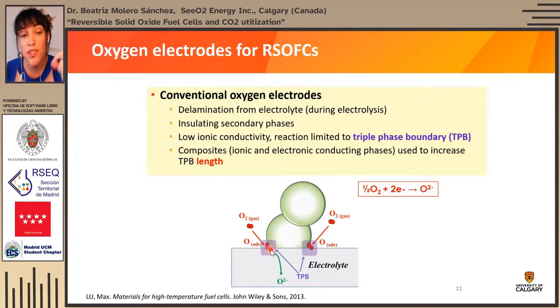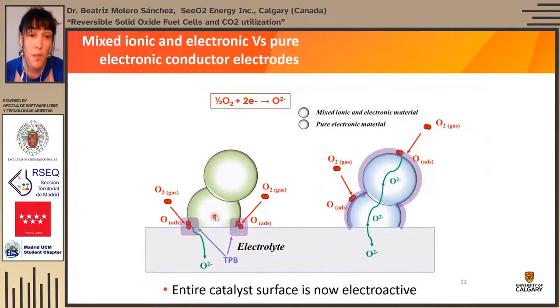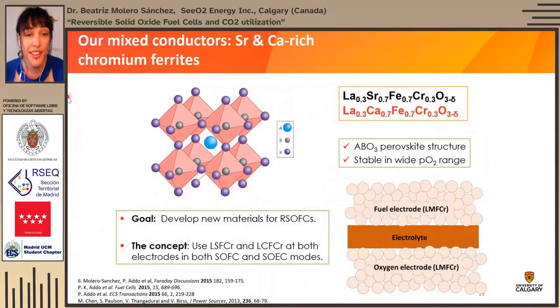Because of that, people started using composites to try and meet those conditions and to increase that triple phase boundary length. So we started looking into what are called mixed ionic and electronic conductors. The reason being, as I mentioned, with pure electronic and conventional materials, the reactions are limited to these TPBs down here. But when you have a mixed ionic electronic material, now you're extending the surface where the reaction can take place to the entire surface of the catalyst. So you're really extending that reaction area. We started working on different composites and compounds, and we landed on these mixed conductors: strontium and calcium rich chromium ferrites. The goal here was to develop materials that could be used for both the fuel electrode and the oxygen electrode.